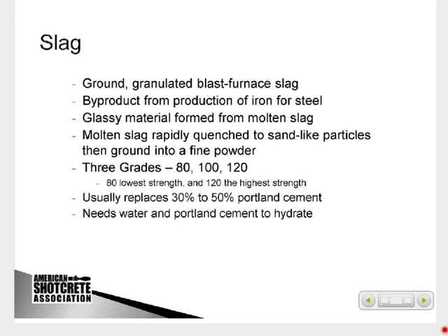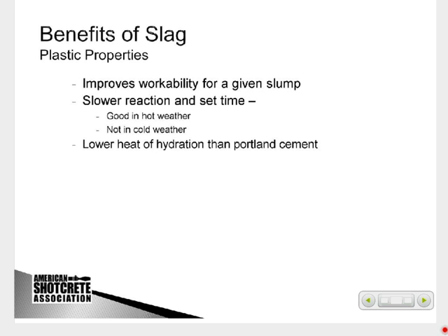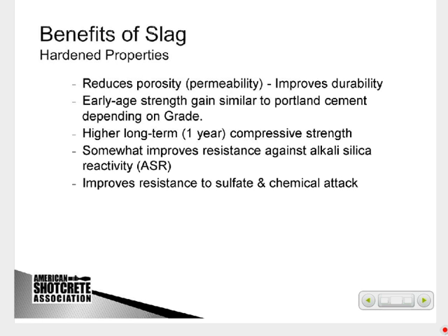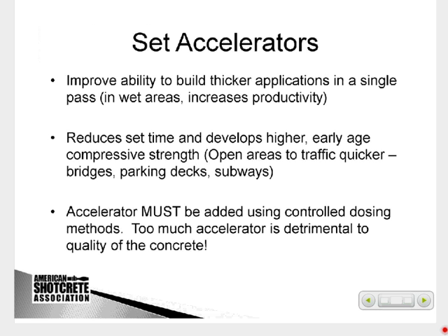Slag is another SCM that I've seen being used more commonly, generally a grade 120, and has been used in shotcrete at 30 to 50% of the cement replacement. It also has a little bit slower set time. It builds strength about the same as cement, but has a lower heat of hydration. Reduces permeability, that increases durability, and does have a little bit of ASR resistance, not as good as fly ash apparently.